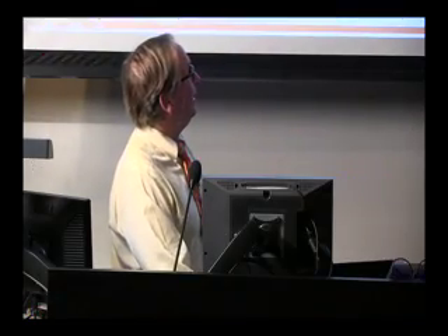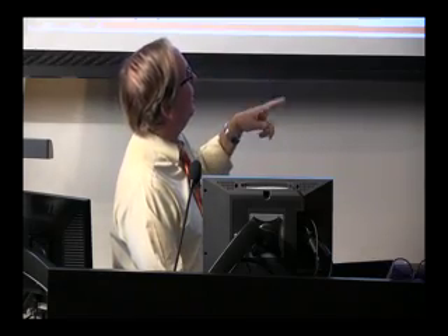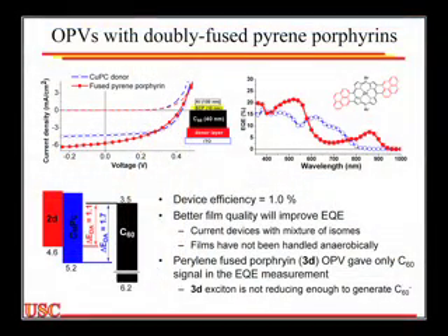So it's not limited just to pyrene. The same approach works for naphthalene, works for coronene, works for perylene. It works for every fused polycyclic aromatic we've put in the meso position. Again, quantitative yields, mixture of isomers between syn and anti, but the reaction works quite nicely. So if we take these four and compare them, and this is now the naphthal derivative, the pyrenyl derivative, the perylene derivative, and the coronene derivative. The two that are the most redshifted are the perylene derivative, which is at 900 nanometers in solution, and the pyrene derivative. If we look in thin films, they redshift even further, and so now we're getting right where we want. The pyrene is at about 900 nanometers, perylene at about 960.